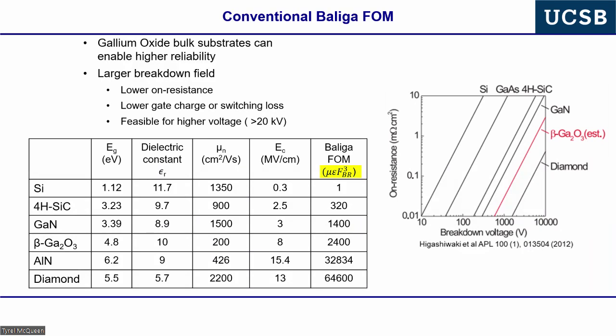So you see the band gap going up here, and this looks at electron mobility, predicted using this sort of parabolic square law for breakdown strength. And then he put these into what's called a figure of merit from Jay Baliga. This is something that Jay Baliga at NC State developed a little bit over 40 years ago. In fact, he probably developed this when he was working at GE Research. And this is looking at essentially how you minimize the on-state resistance while holding a large off-state reverse bias voltage.